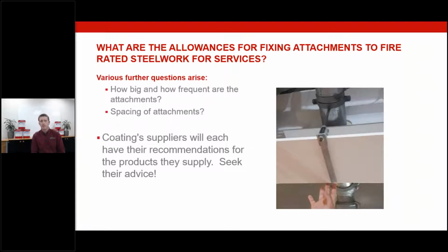But generally speaking, these items are pretty small. What you're doing there is minimizing the amount of area that you're exposing to the actual heat that would provide a heat sink or failure point in the main beam itself. So those individual attachment points will be pretty small. If they go exceeding that, you've either got to find another way around them, or for any direct attachments, you have to overcoat that with the intumescent coating itself to the same dry film thickness as the main member that it's attached to.